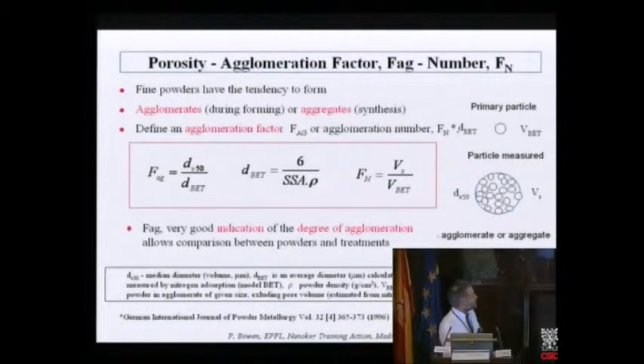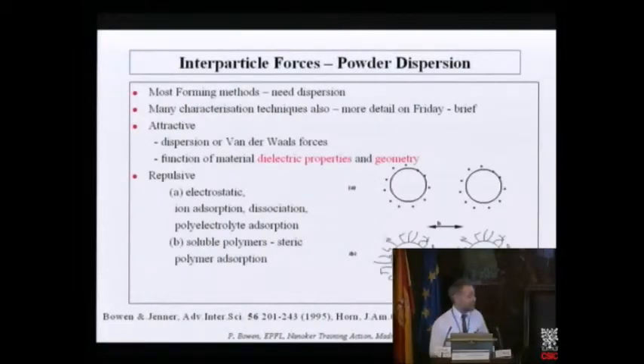So from the BET, we can calculate the volume of a primary particle. And if we know the volume of the solid material in the aggregate, we can then take the ratio of volumes, and then we get the number of primary particles in the aggregate, so we get an agglomeration number. How many primary particles are in the aggregate. To do this, you need to know the porosity of your particle, which I generally tend to do using nitrogen adsorption desorption. We can get a porosity from this aggregate, but it's not necessarily easy. But these give you a way to actually quantify the state of aggregation.